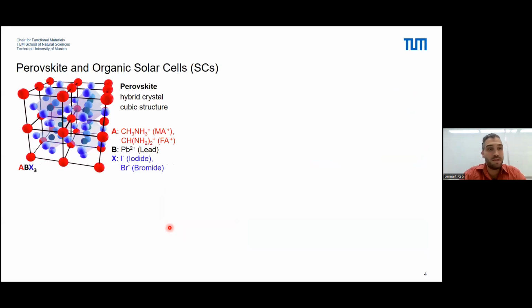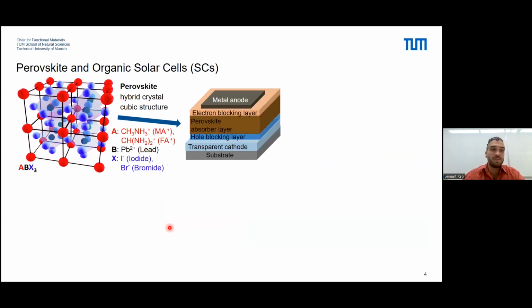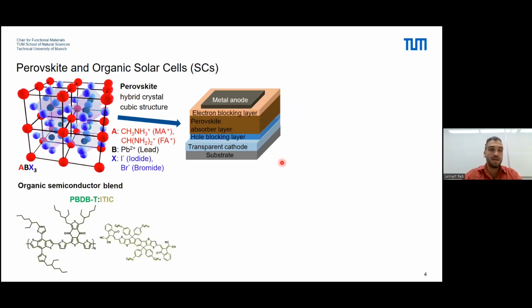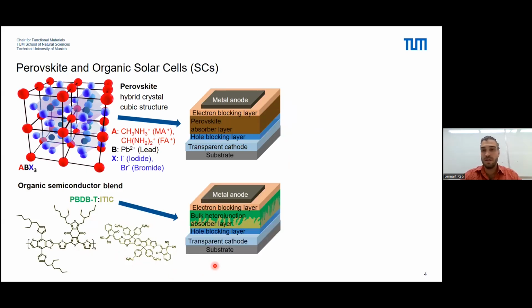Let's stick to this, and I will quickly just introduce perovskite. So it's a hybrid crystal structure, as you all might know. And this material is creating the absorber layer in a solar cell sandwiched by blocking layers. And then you have the electrodes that complete the stack, all deposited on a substrate. In organic semiconductors, usually one is using a blend of donor and acceptor. In this case, it's a small molecule acceptor, and they form a bulk heterojunction absorber layer. And the stacking apart from that is kind of similar.